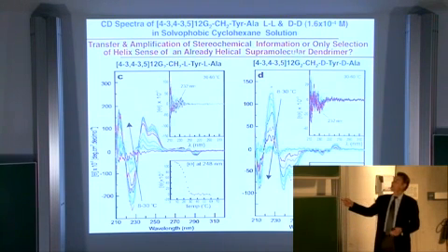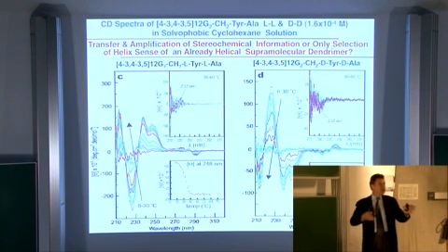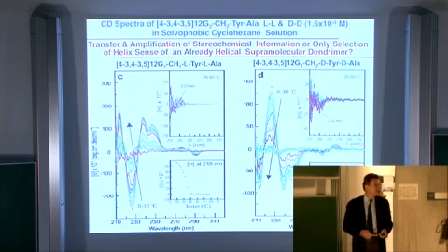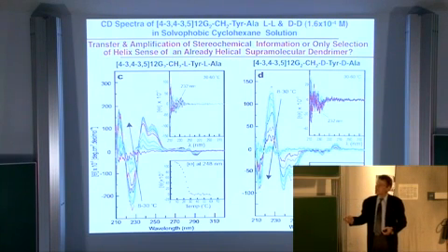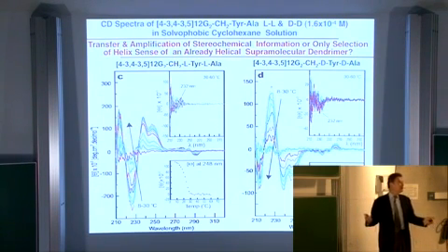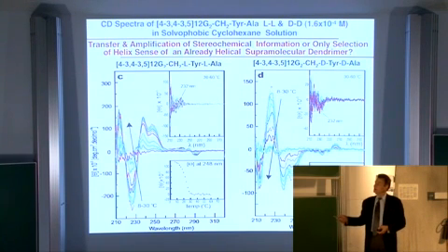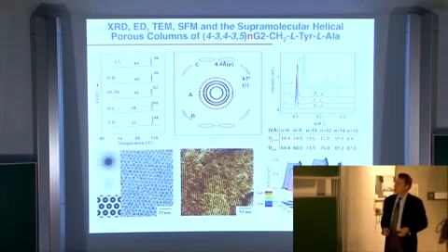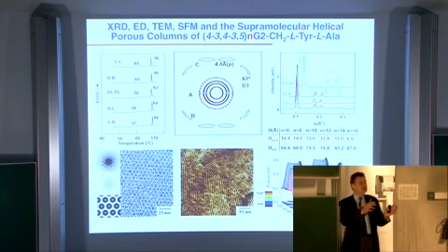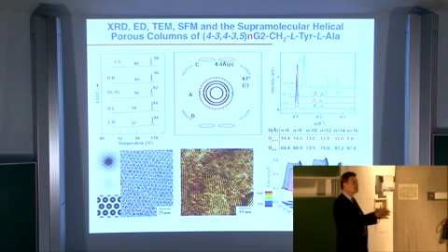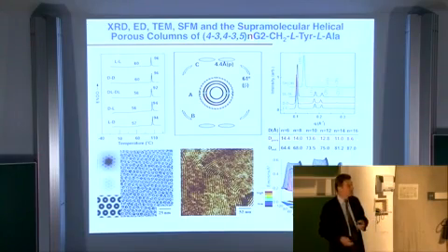And we demonstrated, without going into any detail, that the second is the situation. As you have seen by X-ray diffraction experiment, generated from non-chiral structure, we could see that, in fact, they are all chiral, except that they are racemic, and therefore the dipeptide just selects the sense of the helical conformation. Without going into any details, we show that the conformation of the assembly is the same in solution and in solid state. It's shape persistent. We solved the structure in solid state.